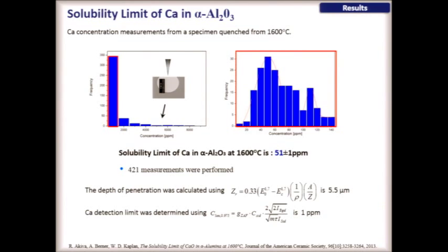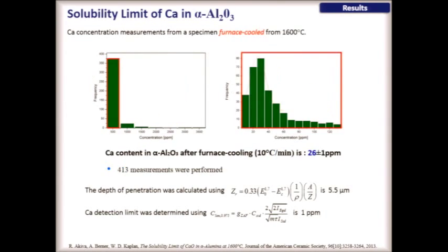This, by the way, is 421 measurements, this data set. The detection limit here is 1 ppm, so we don't have a problem with detection limits. Okay? Yes, this is furnace cooled. This is when we cool it in the furnace and we get a 26 ppm.